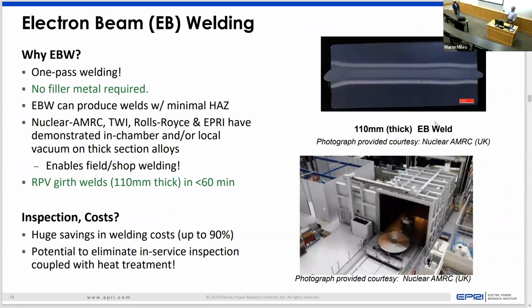Another question. A bit of a clarification about electron beam welding. Obviously, there's no filler material, so you don't need V-notches; you just make two surfaces flush, and the electrons go right through the center of it, so the max distance is just the furthest the electron is going to travel and correctly melt the material. Yeah, let me go back to that one picture. You can see the electron beam weld here at the top. That's about 4 inches across, I think. That's a pretty thin weld that's been butted together, and essentially it just melts what's in the center. There are laser processes that we also work with that we've had mixed results on. They're not nearly as effective right now as electron beam welding.